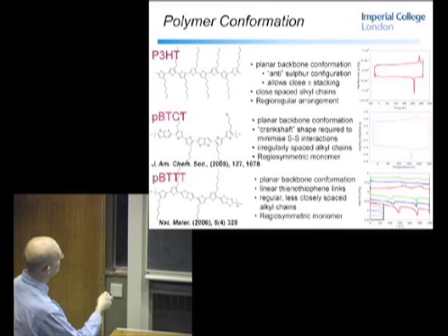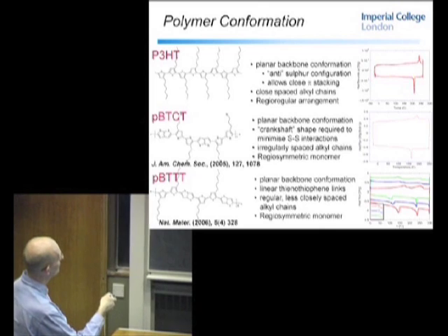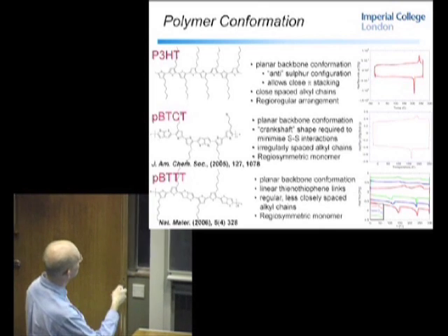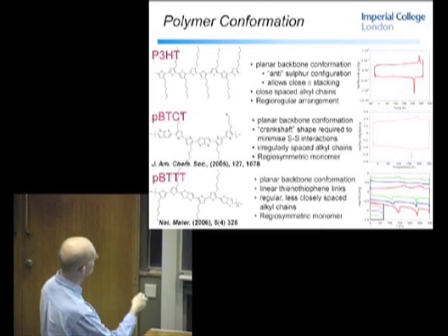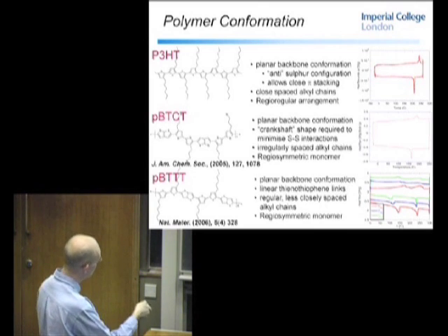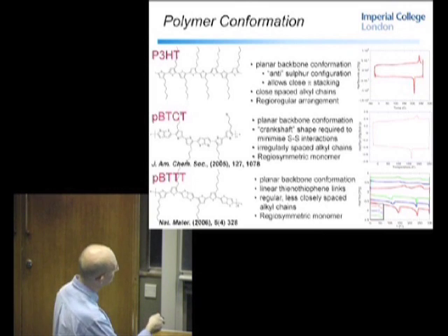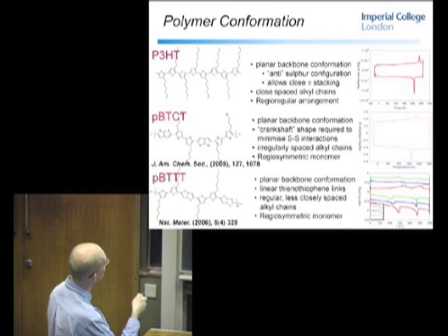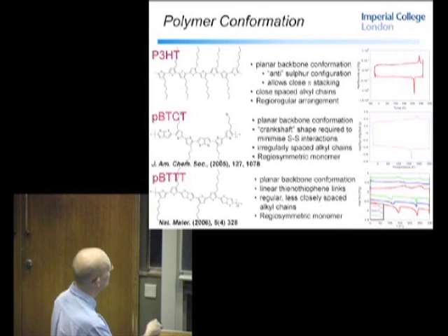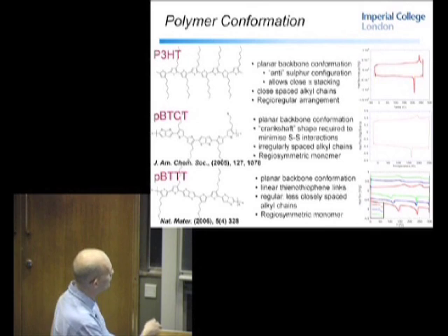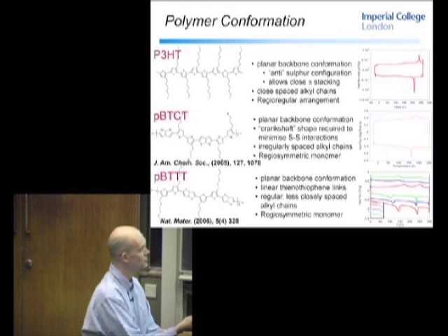But one other feature about this material is that it's regiosymmetric around the thienothiophene, so there's no issues about regioregularity. So this is a symmetric repeat unit. This unit is also a symmetric repeat unit. In this case, the backbone is a little bit more regular in shape, not quite as linear as P3HT, but the conformational freedom is reduced because, again, we've fused these thiophene units together, and this actually helps charge carrier mobility.